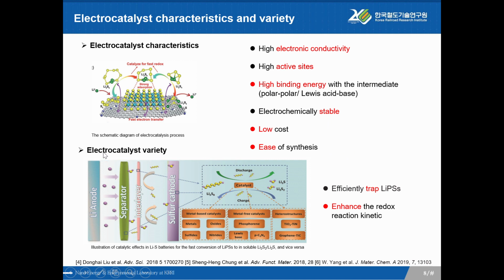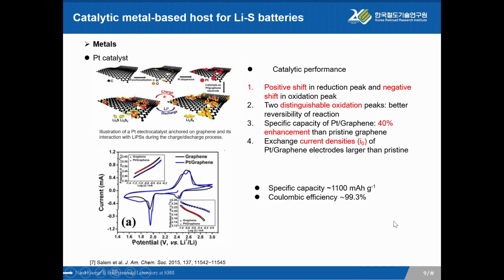Catalysts can be divided into metal-based catalysts such as metal oxide, sulfide, nitride, and metal-free catalysts like phosphorene and Lewis base and heterostructure. All the catalysts should efficiently trap lithium polysulfide and enhance the reduction reaction kinetics. The following are some typical examples. First is metal catalyst, Pt. The Pt particles are dispersed on graphene.